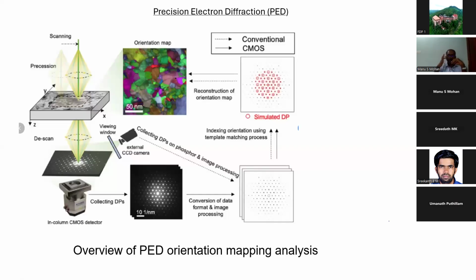Then that pattern is compared with the already stored simulated pattern. Basically in EBSD, some of you have already done EBSD, so you are aware of how the pattern is obtained. You compare with the already generated Kikuchi patterns, which will be compared with the acquired Kikuchi patterns, and if the Kikuchi patterns are matching, you give a color code. These Kikuchi patterns are generated using CIF files. CIF files have the atomic coordinates, the space group, and the lattice parameter information.